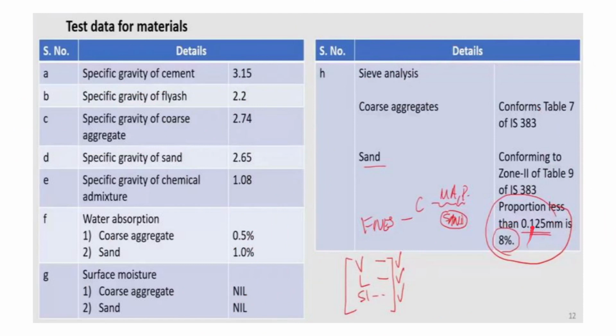As I told you, the fraction finer than 0.125 mm in the sand is taken as 8% of the sand. So if 100 kg of sand is there, we assume that only 8 kg of sand has a size less than 0.125 mm.